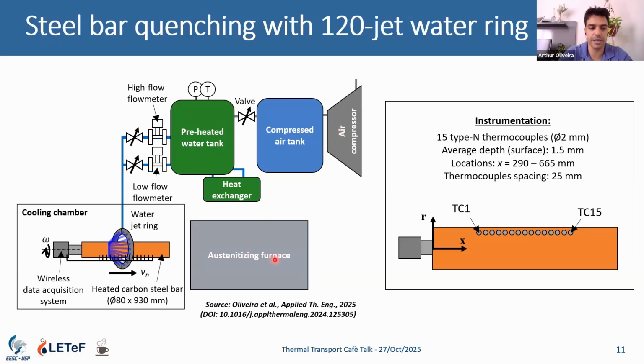You have here the furnace, the bar cooling section, the water line, and the water is pressurized by the compressed air, so you control pressure and temperature of the water aspersion over the part. In this case, I'm going to show the results for a steel bar, an 80 millimeter diameter bar, approximately 1 meter long.